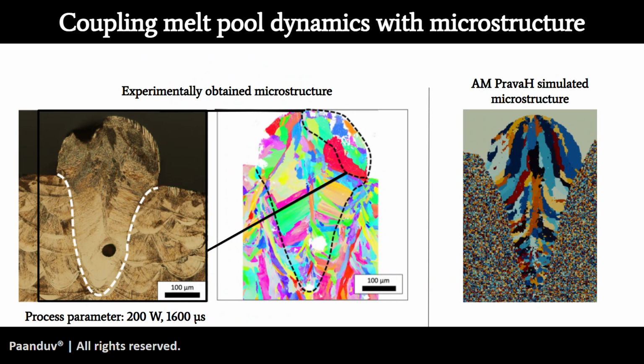Again, all these images are mere colorful images if there's no validation data, real images, real experimental data to validate them against. What we see on the left hand side is a real bead, and what we have in the center of the screen is the EBSD microstructure data from that bead. So the first two images are coming from the experiments, and just look at the third image, which has come from pure simulation from AM PravaH's microstructure module. Just look at the excellent overlap